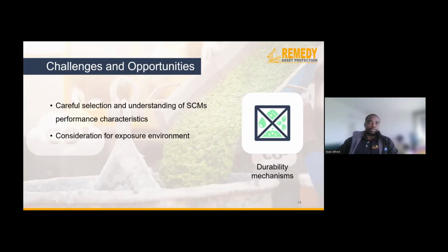If we look at the aspect of the durability mechanisms, we see that studies have shown that SCMs like fly ash and slag can enhance durability performance, but this enhancement actually relies a lot on the proportions that are used and the specific environmental conditions. And what is critical to understand here is that the difference in the chemistry of these materials means different rules. For example, a higher SCM content can enhance chloride binding, which can contribute, of course, to corrosion resistance, particularly for high alumina content SCMs like GGBS and metakaolin. But on the other hand, SCMs like fly ash and silica fume do not necessarily have as high an alumina content, but improve the pore structure of the concrete, thereby reducing the permeability.